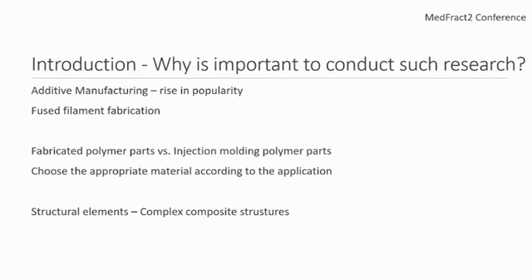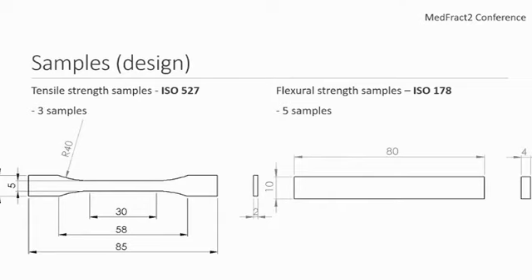There is a lot of research in this area, but we did not find much research that compares different materials. Most of it compares the process parameters. So we designed the samples according to the standards for polymer parts. According to the standard ISO 527, we designed the samples for the tensile strength, and we designed three samples for the experiments. For the flexural strength samples, we used ISO 178. As you can see in the picture, those are the samples.